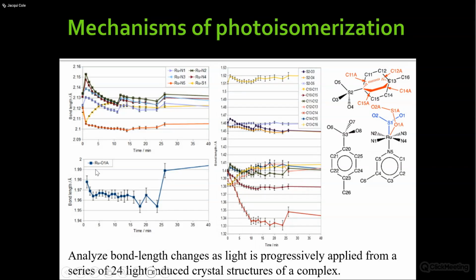If you look at the ruthenium-oxygen bond, that's the oxygen 1A, the oxygen of the oxygen-bound sulfur dioxide group, the oxygen that's coordinating to the ruthenium, there's a really big jump at 26 minutes. So something strange is happening with the oxygen-bound sulfur dioxide photoisomer at 26 minutes, which we'll come to in a second. And at 11 minutes, the carbon 13 to carbon 14 distance really shoots down, and carbon 10 to 15 does as well. That's in this area here, the arene that's rotating to alleviate the strain. So something is happening at 10 to 11 to do with the arene, and something at 26 minutes to do with the oxygen-bound photoisomer.